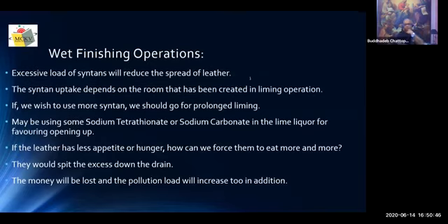Excessive load of Syntan will reduce the spread of leather. We believe that we can build up anything if we just pump Syntans into the leather. But Syntan uptake depends on the room that has been created in the liming operation. If we wish to use more Syntan, we should make more room for it. That means we should go for prolonged liming.